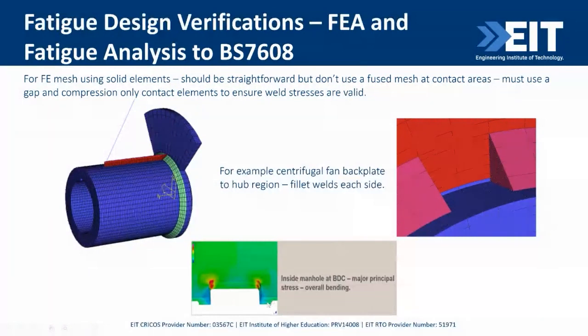But you must make sure that you don't fuse gaps in your solid elements. So this is going back to the model we saw with the doubler manhole and the welding around inside and outside of that doubler, where that gap, that lack of fusion on that gap, is simulated. That's the same here with this back plate shell element. It's not fused and joined into the hub because it won't be. It's only joined into the fillet welds on the back and the fillet welds on the front, so you'll load up your welds properly. So that's critical.